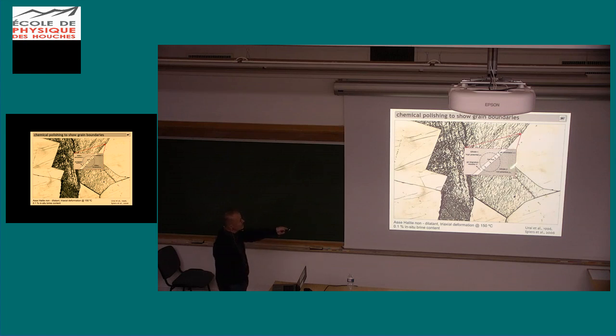These grain boundaries are highly mobile because they have this very, very thin fluid film in them, and if there is a dislocation density contrast on both sides of this grain boundary, then on one side of the grain boundary the solubility in this brine becomes a very, very small amount higher, and that creates an ion flux across this grain boundary. And because this grain boundary is so thin, and because the diffusion in fluid is so high, these grain boundaries can migrate very, very rapidly.